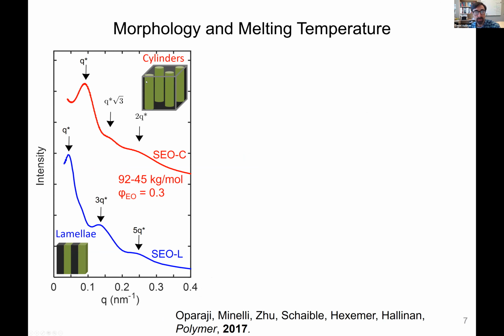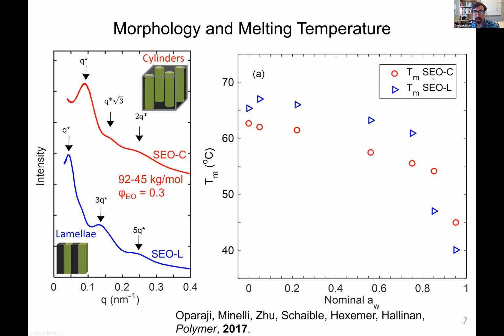So we expect to have PEO cylinders in a polystyrene matrix, and that's what the X-ray scattering tells us. This is, again, that same lamellar block copolymer that I showed you before. So I'll refer to the cylindrical one as SEOC and the lamellar one as SEOL.